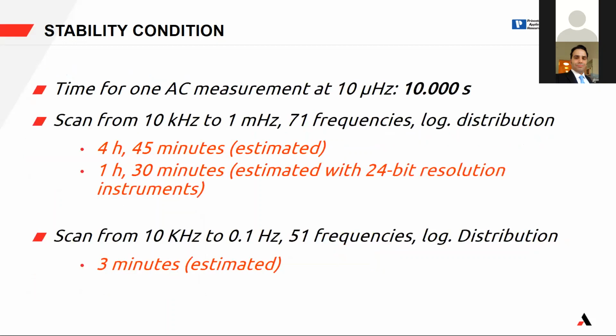How long can it be? These are some examples. Keep in mind that doing one single frequency at 10 microhertz will take 10,000 seconds, so more than 3 hours. And it's one. Sometimes the instrument wants to do another one, because one is not very good, and that's another 10,000 seconds. And a scan from 10 kilohertz to 1 millihertz, 71 frequencies with logarithmic distribution, will take an estimated 4 hours and 45 minutes. With 24 bits resolution, a new technique that people are using in some instruments, it will take 1 hour and 30 minutes. It's faster. If you do more or less the same number of frequencies from 10 kilohertz to 0.1 hertz, it will take 3 minutes.